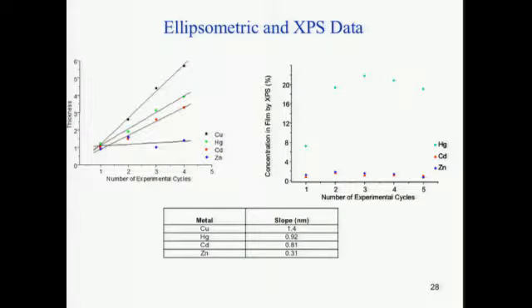I'm not going to bore you with all the details, but I will say that the periodic trend, they got it right, the guys who came up with the periodic table. So we saw that with copper and mercury, we could get a multilayer. Using XPS, we also looked at the relative concentration of the different metals within a multilayer system. We found that after the first layer, cadmium and zinc are not incorporated into the multilayer. However, mercury is, and you start to see a drop-off, which I think is probably due to attenuation as you grow the number of layers.